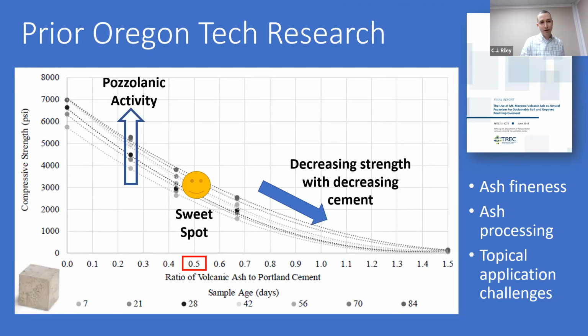They effectively showed that the arrow, the upward pointing arrow on the left, tells us that pozzolanic activity is happening, that the mortar cube would strengthen up to 28 days, the dark circles, and beyond that would continue to gain strength, which is indicative of pozzolanic activity. It was clear and expected that the strength of those mortar cubes would drop as the ratio of volcanic ash increased. And so we identified a sweet spot here at right around 50-50 ash to cement in the binder that we would use.